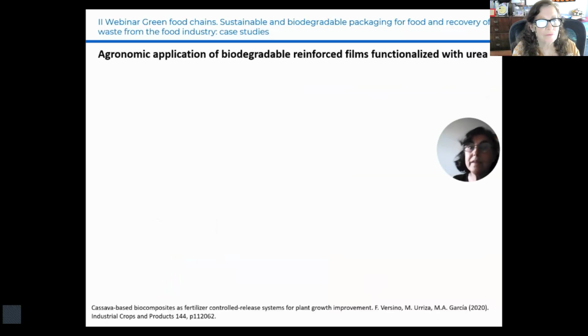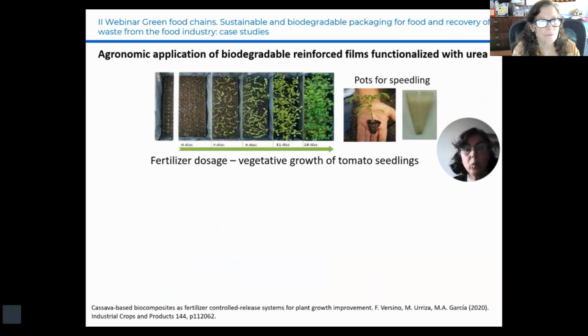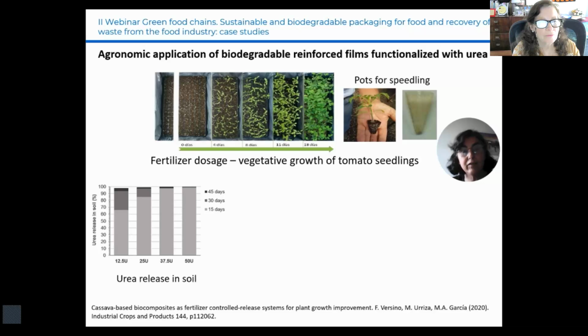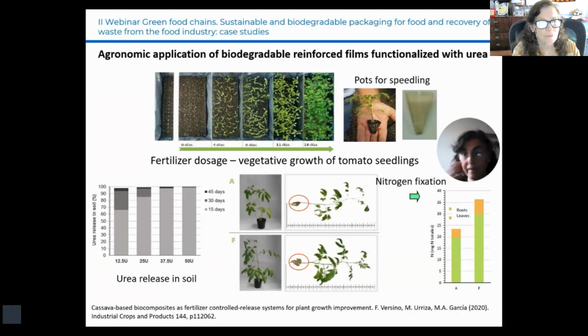These materials were functionalized with urea, allowing the controlled release of fertilizer within a time frame compatible with the growth cycle of tomato seedlings. These active films were used in an application for tomato cultivation, both for developing pots for seedlings and for supplementing the pot containing the seedling. It was observed that the pot with the dispensers allowed for better plant development, as you can see in figure B, with a greater nitrogen fixation in the roots and leaves, and a larger leaf area. This indicates that this plant had better development, resulting in increased crop productivity.